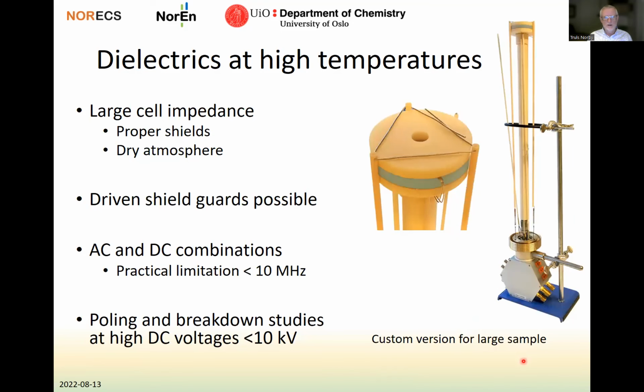You can use the ProboStat for insulating materials and dielectrics at very high temperatures also. The ProboStat has a large cell impedance, so you can measure insulating samples and samples with low capacitances. It requires that you operate your shields properly, and you can, for instance, use dry atmospheres to reduce surface conduction and capacitance by water. You can also use driven shield to guard against parasitic conductance. You can use AC and DC combinations, but the ProboStat is typically limited in frequency up to 10 megahertz. You can do poling and breakdown studies at high DC voltages up to 10 kilovolt in the high voltage version of the ProboStat.